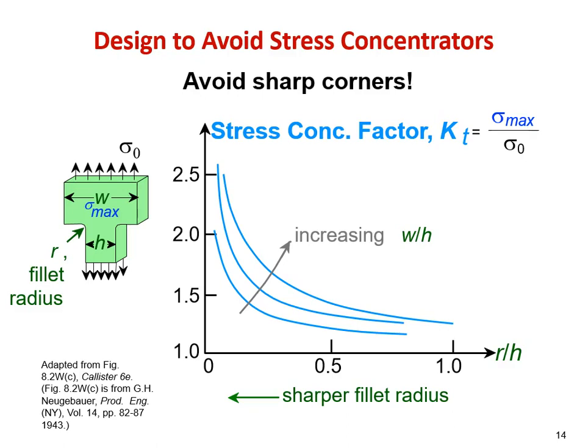And from the standpoint of fracture and material failure in general, we want stress concentration factors in our designs to be as low as possible. We really want the average applied stress to be the highest stress in the part for any design. That's obviously never going to be true, because we can't design perfect smooth parts with no section thicknesses, but we certainly want to keep those KTs as small as possible, because they can have enormous consequences on the stress state in an actual real design and push us over yield, or, as we'll see as we go along, get us into a state where we're going to have a fracture problem.